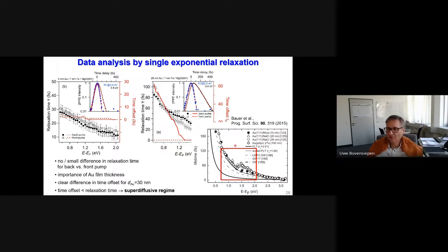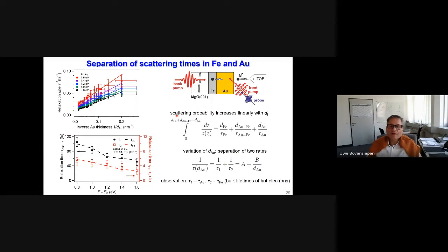And I show here reference data from literature for bulk gold, and the red frame is essentially the energy range that we analyze. So let's look here at the low energy part where we see that the lifetime in bulk gold is 120 femtoseconds. And this is longer than for both respective values that we identify here. So how can that be? Do we not have clean gold layers or what's going on? Well, we have to understand that we investigate a heterostructure.